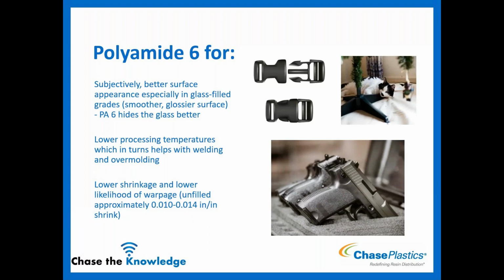You also process it at a lower temperature. It has a lower melt than 6,6 does. Therefore, you process it at a lower temperature. This then helps if you're going to do anything after the fact, maybe a secondary operation like welding. So when you weld or when you overmold, you have to get the surface to melt again so you can get it to either stick to itself when you're welding or get a TPE, some variant of a TPE, to stick to it. You have to melt the surface of it. So if it's a lower temperature material, you have to get it to a lower temperature for it to melt to then weld or overmold. So 6 is preferred in those applications.